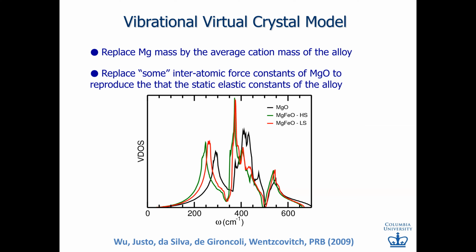At that time, we couldn't calculate the vibrational density of states or the phonon dispersions of solid solutions because we needed DFT plus U. So we developed a vibrational virtual crystal model where the cation mass, as you can imagine, is the weighted average of the end members, as well as the elastic force constants. The force constants between first neighbors were also averaged with the weighted average of those of the end members.